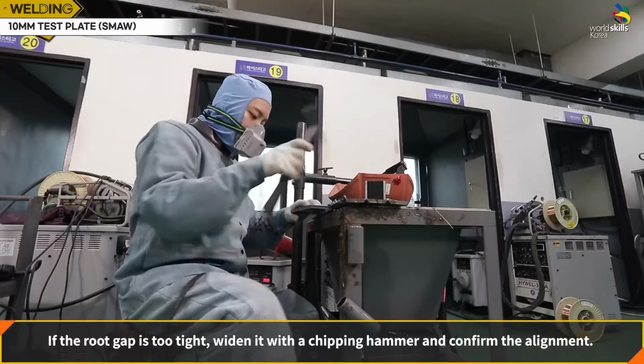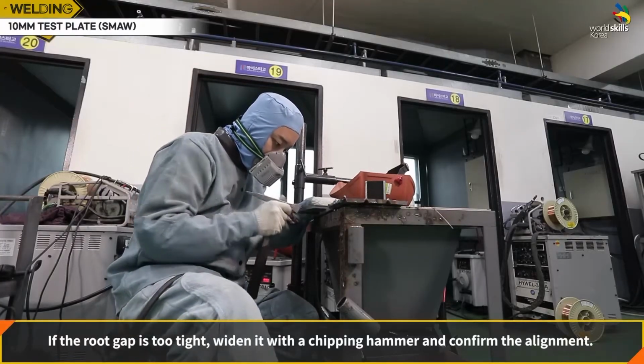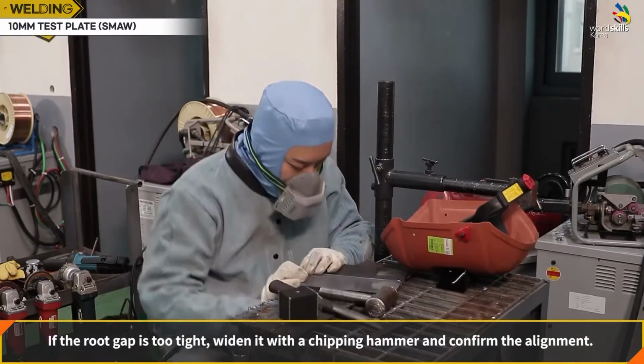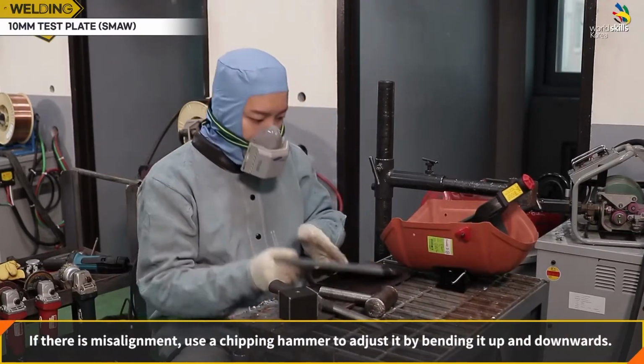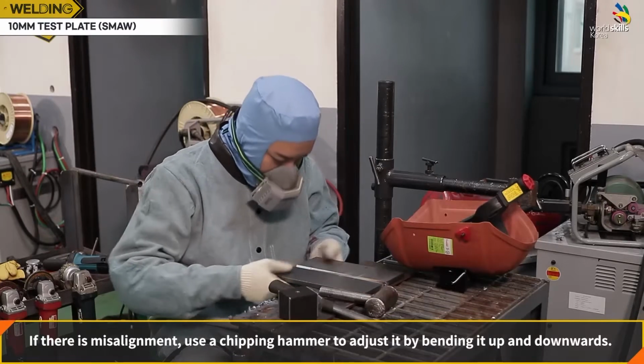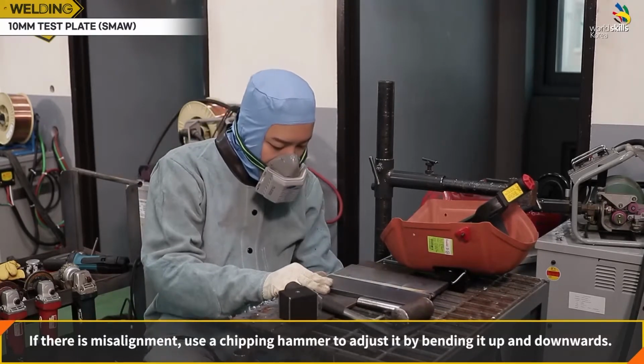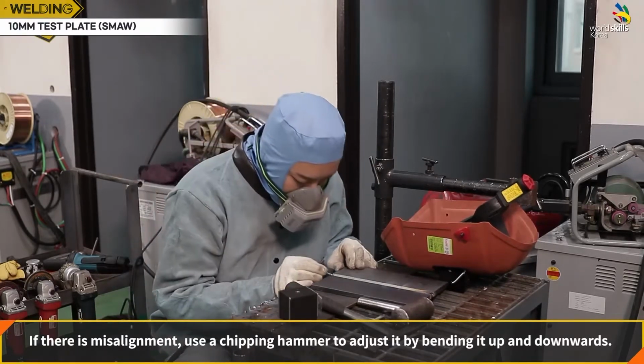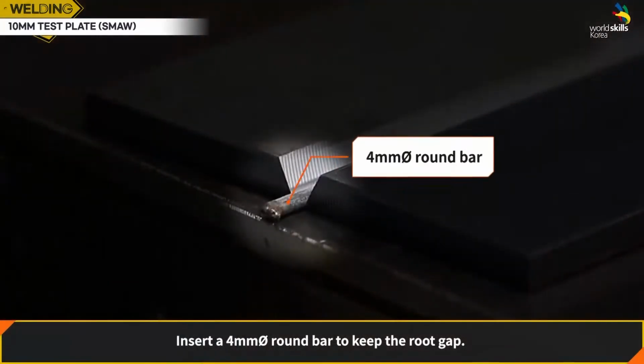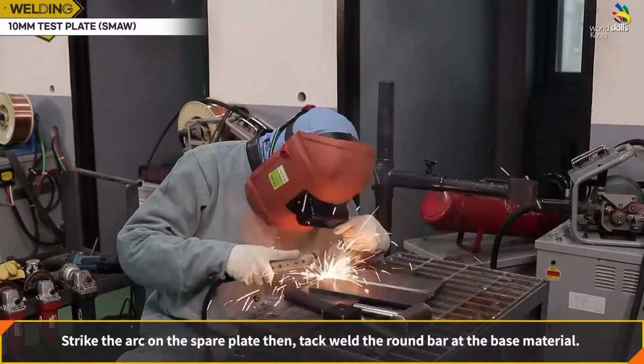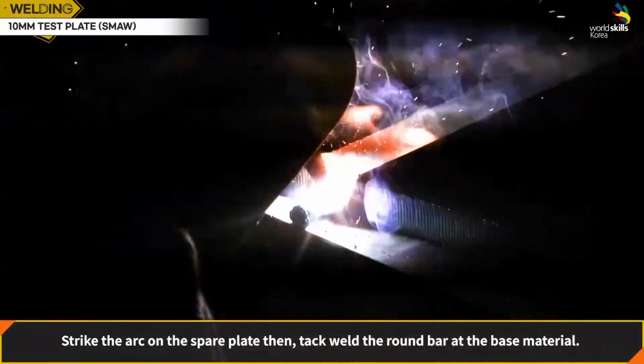If the root gap is too tight, widen it with a chipping hammer and confirm the alignment. If there is misalignment, use a chipping hammer to adjust it by bending it up and downwards. Insert a 4 mm round bar to keep the root gap. Strike the arc on the spare plate, then tack weld the round bar at the base material.